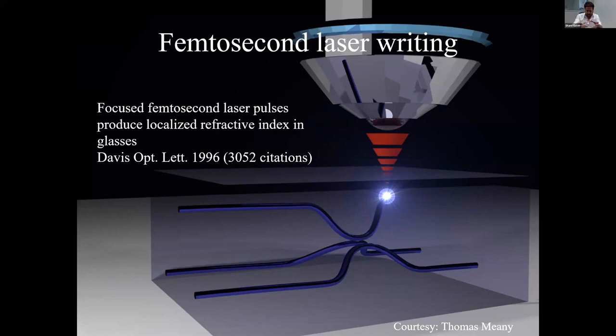So if you then scan the sample relative to the fixed focus femtosecond laser beam, you can form optical waveguides, where you have a higher refractive index within the modification compared to the pristine glass. The advantage here, compared to any other technique, is we can form these structures in 3D, which is quite compelling for photonics. This work has been cited over 3,000 times already, mainly related to fabricating glasses, but also polymers and certain crystals. But up until my research, no one had ever addressed diamond.